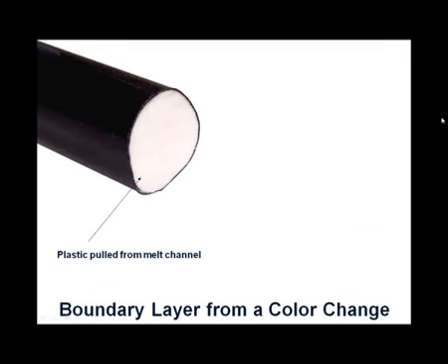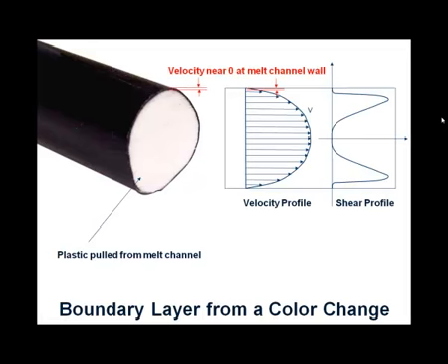For example, this is a perfect picture that shows some plastic that was pulled from a melt channel. As you can see, the inside, the core of the melt channel, is perfectly clean. It's perfectly white. There is no black color in there. But the actual melt channel is covered by a black layer. Why? Because, as we were saying, the speed of the resin very close to the wall of the machine is basically zero, so it's actually not moving. So it is extremely difficult to remove.